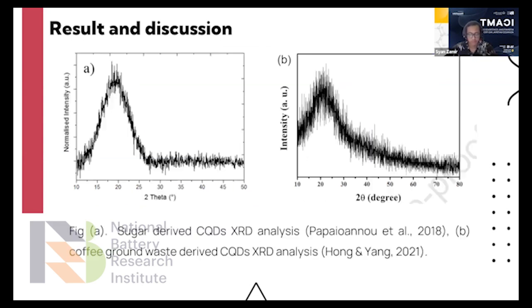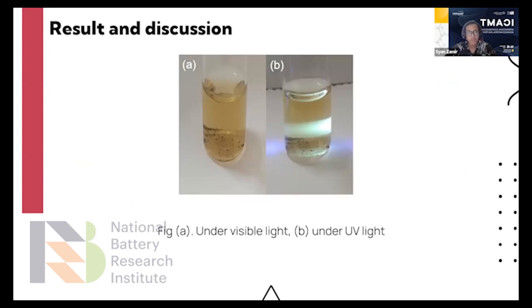Based on reference from previous studies, carbon quantum dots derived from coffee grounds have a peak at 2 theta equal to 24 degrees, and carbon quantum dots derived from sugar have a peak at 2 theta equal to 21.21 degrees. This is a qualitative test of solutions that contain carbon quantum dots by firing UV rays with 365 nanometer wavelength.